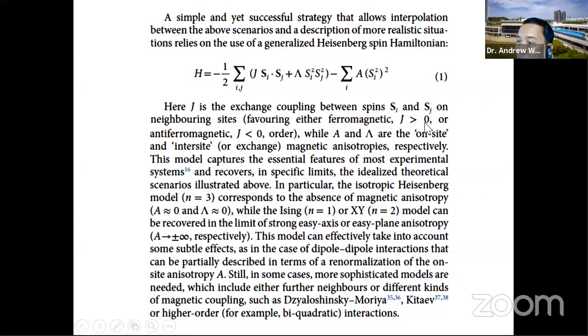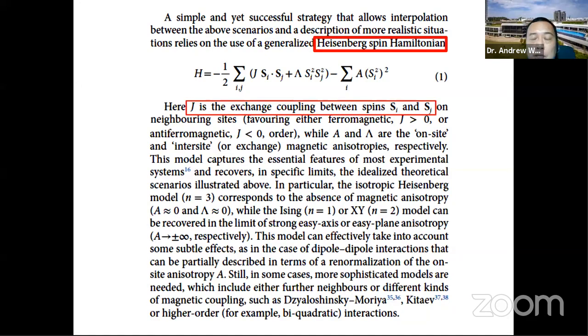So let me first talk about, so this is the only equation I'm showing. This shows the Heisenberg spin Hamiltonian for a magnetic system. You can see that the first term, J, is the exchange coupling between nearest neighbor spins. That is the common term we always see. But there are additional terms, A and lambda, and these are on-site and inter-site magnetic anisotropies. These two terms relate to anisotropies, whereas the first term relates to the exchange coupling. With J greater than 0, you get ferromagnetic materials, and less than 0, you get anti-ferromagnetic.